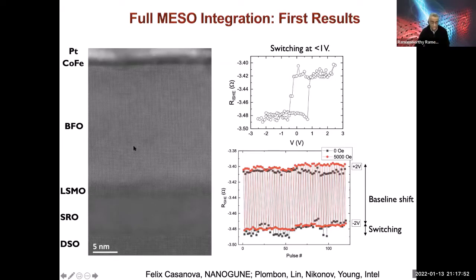And you can see these are still epitaxial structures. We haven't gone to polycrystalline yet. Cobalt iron is our ferromagnet, and platinum is the SO part. It's the large spin-orbit coupled metal. And we can indeed see switching of the inverse spin Hall effect.